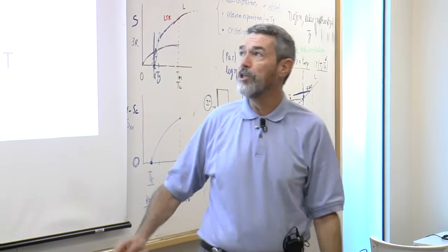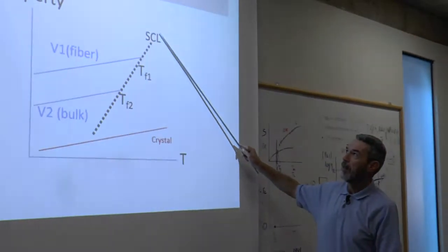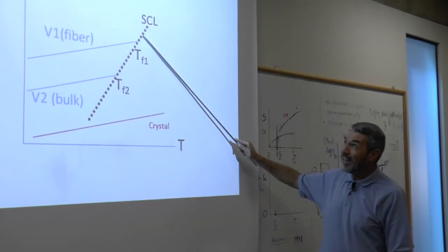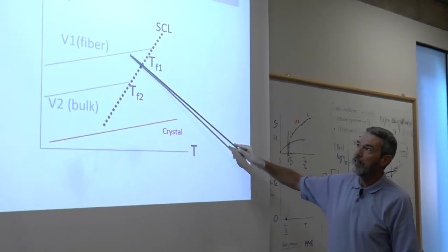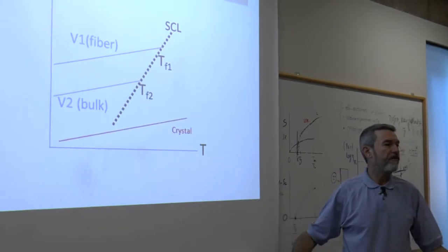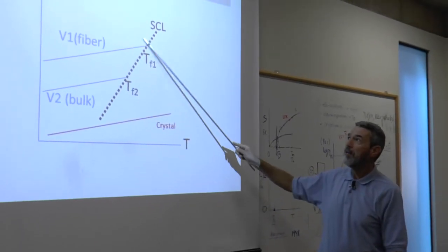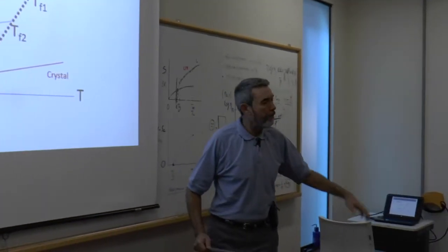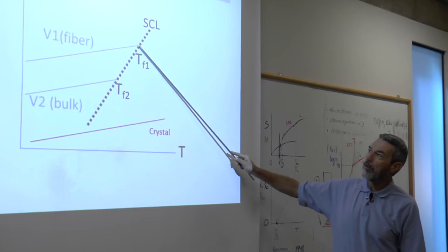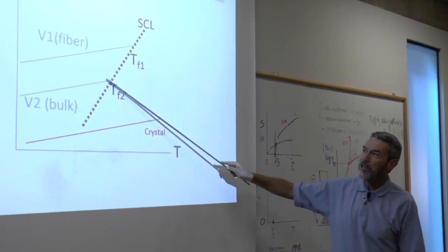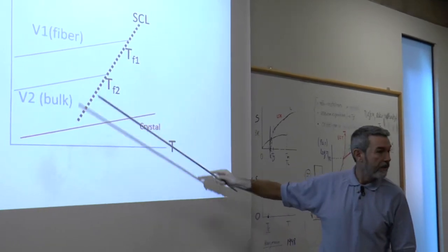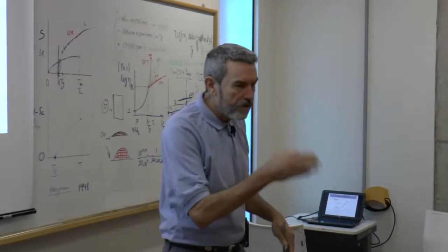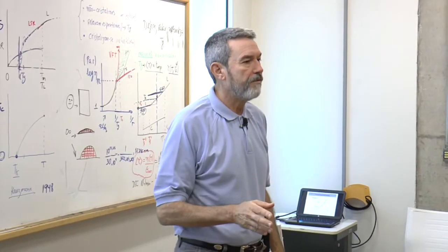If we measure TG on the cooling path, coming from the supercooled liquid exactly with the same speed as we did to produce the fiber, the TG will be similar to TF1. If we do it on the cooling path with a much slower cooling rate, maybe the TG will be similar to this one. But in the general case, TG is not identical to TF.